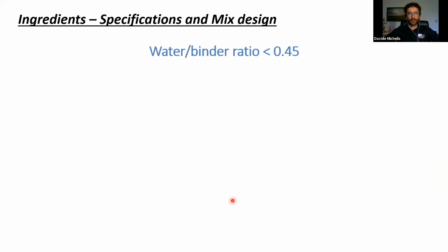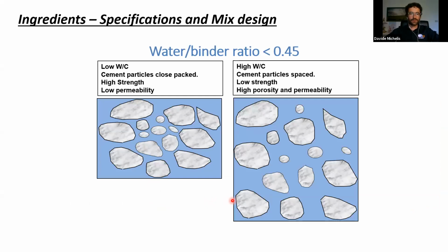This is a scheme that I love to use, because it really shows the concept of water cement ratio. On your left side, you see a low water cement ratio mix design, and you see that the aggregate and the cement are pretty close to each other. So when the hydration process of the cement happens, there is a better connection between all the components. On your right side, you see a high water cement ratio mix design, and you can understand very well that it's really more difficult for the cement to connect all the particles together. So we are facing a lower strength and, of course, a higher porosity and permeability.